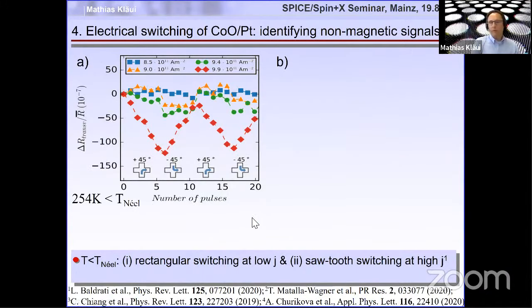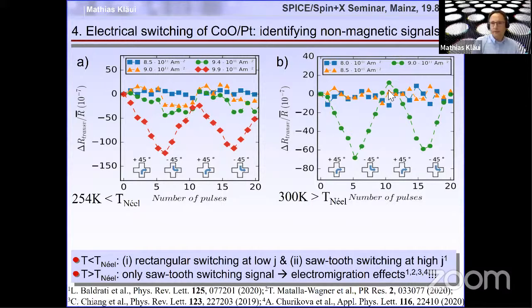To show, however, that there is really a non-magnetic switching, we did an experiment in cobalt oxide, where we can image easily above and below the Néel temperature. Below the Néel temperature, it looks a bit like the nickel oxide. At low current densities, we get the step-like switching, and at high current density, this triangular switching. Whereas above the Néel temperature, we only see this non-magnetic triangular switching, which allows us to identify that this has something to do with electromigration. We are not the only ones who find this. In this work, which just came out last week, the other people also saw, even by imaging, that electromigration in the platinum can be of key importance. And so we now know the origin of this non-magnetic signal, which is an electromigration effect.